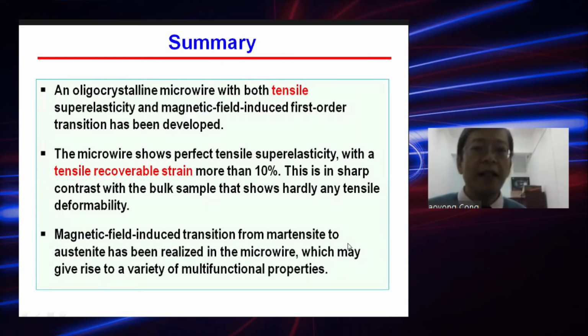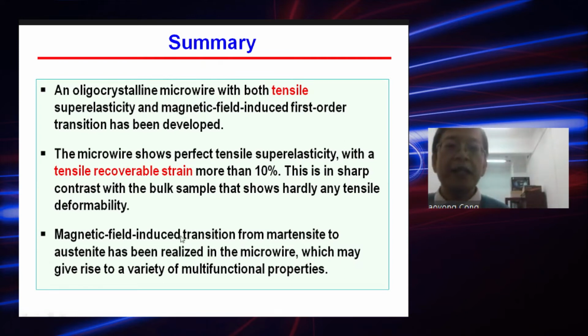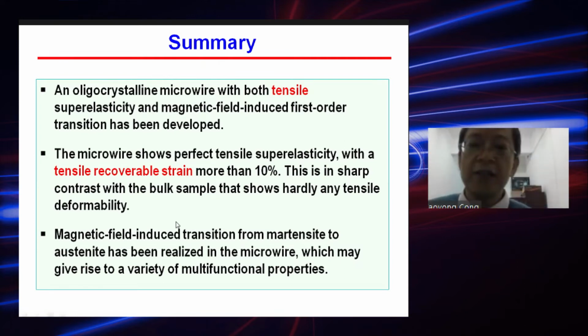With this part, I give a summary. We have developed an oligocrystalline microwire with both tensile superelasticity and magnetic field-induced first-order phase transition. This microwire shows perfect tensile superelasticity with a recovered strain of more than 10%. This is in sharp contrast with the bulk sample that shows hardly any tensile deformability.